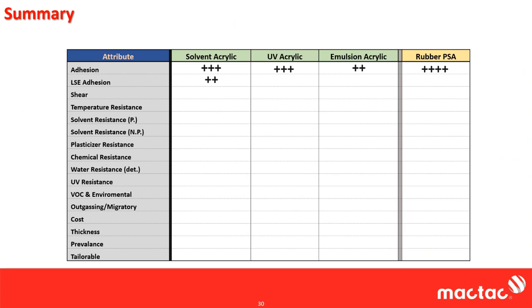In terms of LSE adhesion, so again, same peel tack, but off of a low surface energy type plastic. Again, solvent acrylic, UV acrylics are going to do about the same. You can put tackifiers in there. Emulsion acrylic, you can tackify emulsion acrylics, but again, because of all the other additives that are in there, you're never going to get as high as the other two. And again, because rubbers themselves are low surface energy materials, they're always going to outperform the acrylics there.